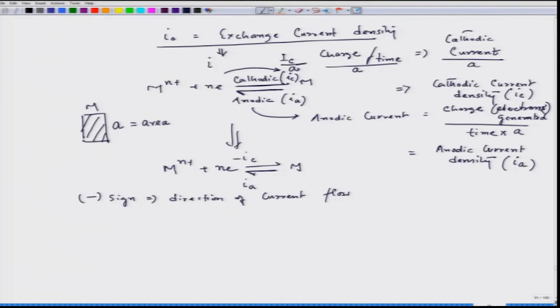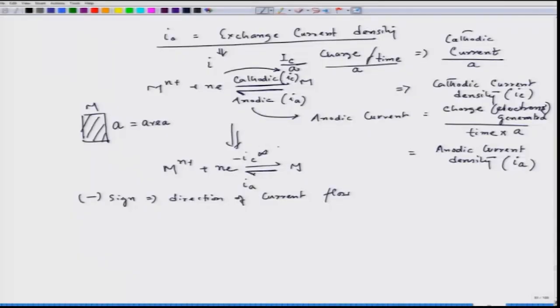So, whichever you take to be positive, the other one should be negative, but what we will take is, IA as a positive current, and IC as a negative current. So, that means it is flowing opposite to the anodic current. Now, we also see that this is proportional to the deposition rate per unit area, per unit time, and this is proportional to the dissolution rate per unit area, per unit time. So, the rate of corrosion rate.